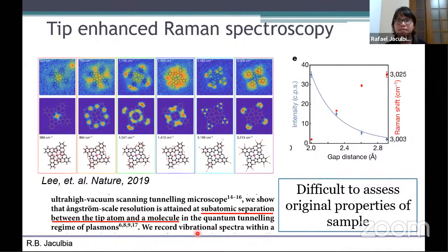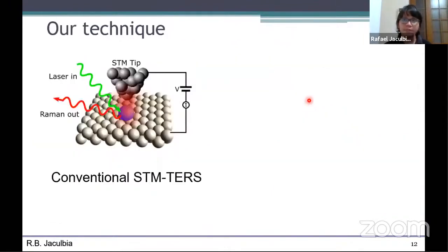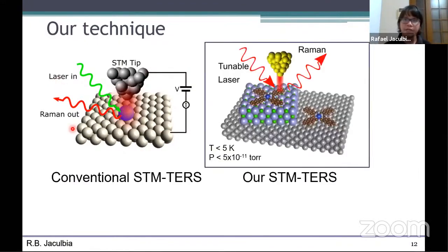And they admit this problem. Well, they didn't point this out as a problem, but they admit that basically the molecule becomes a hybrid system of the molecule and the tip. But if we want to assess the molecule itself, then we cannot use this technique. So in order to solve this problem, the conventional technique was just to place the molecule directly on the metal and then approach the STM, the metal's tip. In our case, what we did is we placed an insulator, sodium chloride, in between the metal and the molecule. So in this situation, the molecule doesn't interact with the metal, and we carefully did not approach the tip very near the molecule.